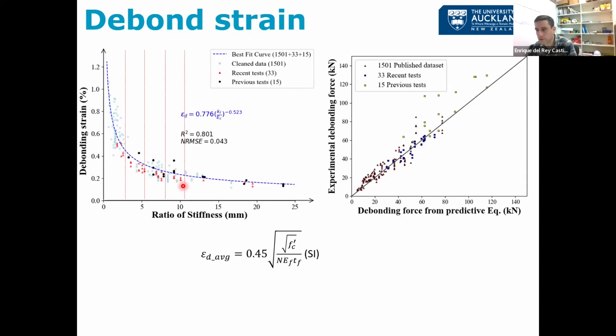And then my student, Junri, put together this equation. So basically it is linking the stiffness of the concrete, the stiffness of the FRP, and with a number, with a variable. The top one is for the average, the predictive equation, probable, and the bottom one is for design. Now you can see it's the exact same thing, just that number changes. And it changes quite a bit. It's like 25, 30% higher, right? So the spread is really big between design and average.